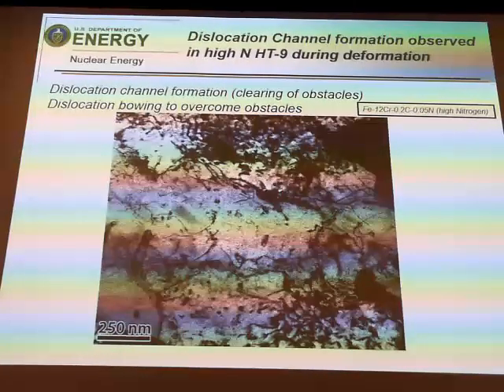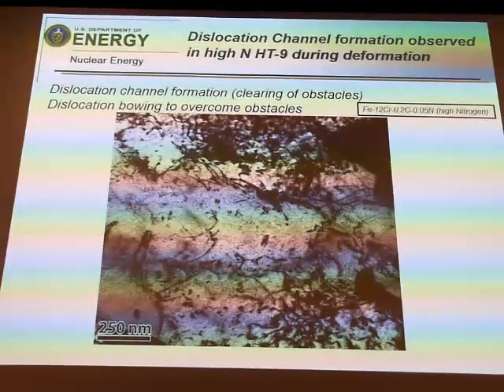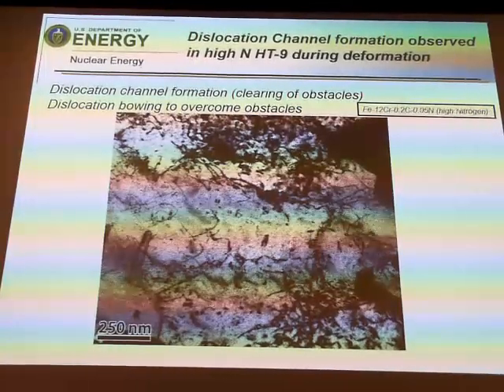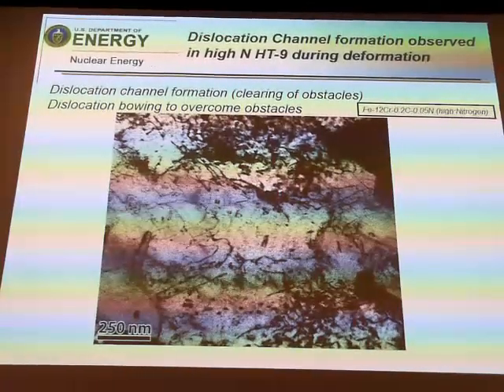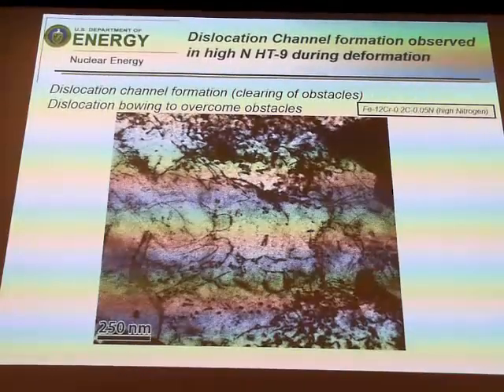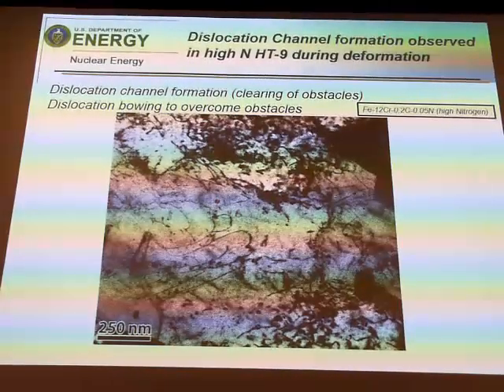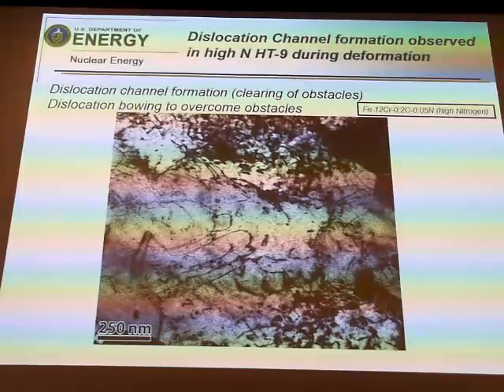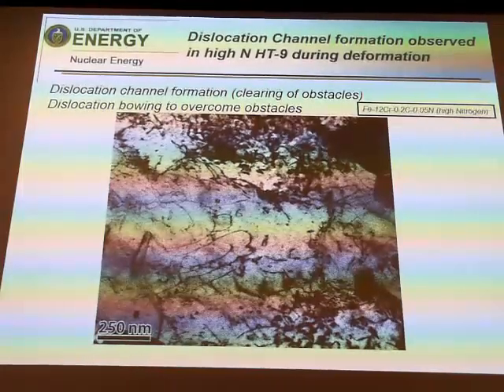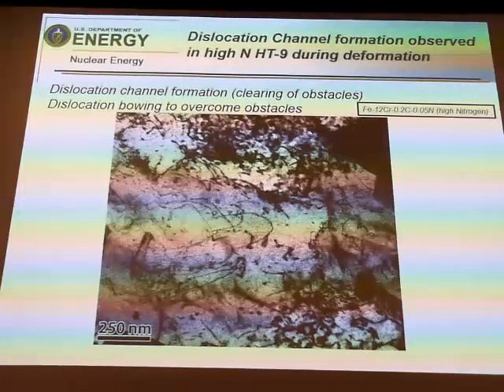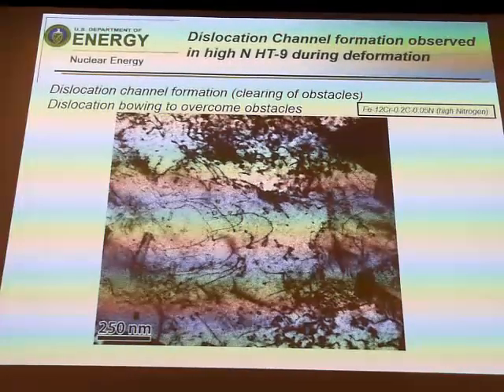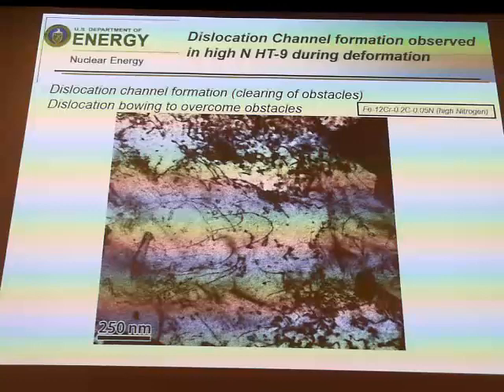You can see one set of dislocations go through, and then another one follow it through the material during deformation. So there's the leading dislocation. You can see it pops through the material, and right behind it you've got almost two or three more moving through the material. So it appears that we're seeing more localized deformation in the case of the higher nitrogen alloy.